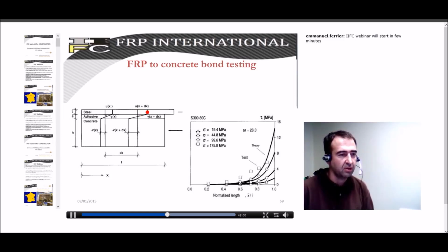When we use a very basic equation, shear is due to the difference of displacement between two materials, steel and concrete, for example, and the angle of rotation is commonly known as the shear strain. You can write those equations in equilibrium between two sections, and this allows you to calculate the shear stress depending on the length. If you do this calculation and compare it to the strain, it's very well developed in the field, in the paper from Täljsten. You can observe that you have a very important shear stress decrease over very few